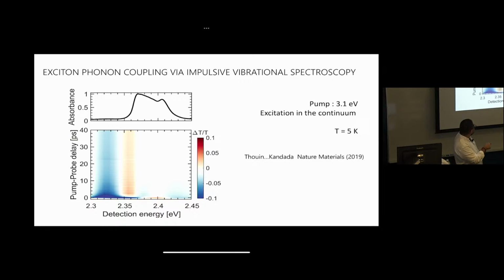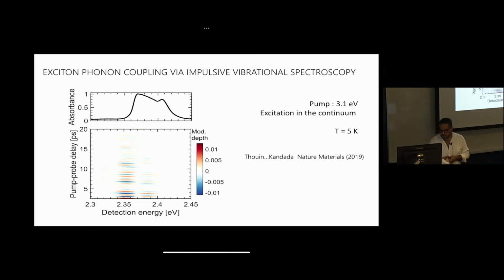But we notice that on top of the line shape, you get these oscillatory components. You get these wiggles, and that's what's called a resonant impulsive stimulated Raman response. You throw away the dynamics. Let's not worry about what the electronic population is doing, and so you just retain the wiggles. Here they are. You've got this oscillatory response. Right at the peak of this exciton, XA, you've got a phase shift. These are classic signatures of resonant impulsive stimulated Raman spectrum. And so that's the signal that you measure.